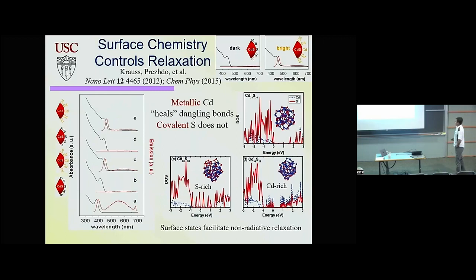What we also learned in collaboration with Todd Krause is that if you think of the chemistry of quantum dots, most of those materials are not stoichiometric. So you have to do something about the surface. When you have perovskites, you can have lead, for example. If you have excess lead, it creates lots of trap states. If you talk about cadmium selenide, as I'm showing here, it's the opposite. You actually want to have metal on the surface, but not the non-metal.